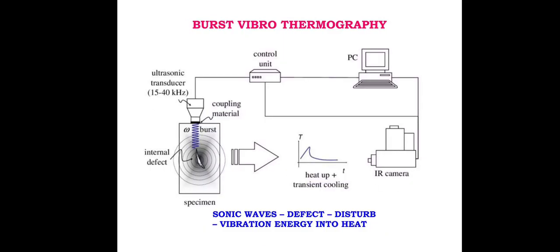Burst vibro thermography. In burst vibro thermography, a burst of ultrasonic waves are injected into the test specimen for a short time varying from milliseconds to a few seconds. This picture shows the schematic arrangement of burst vibro thermography. In this method of testing, the ultrasonic sound wave is produced by a transducer made of a stack of piezo elements and concentrated in a titanium horn that acts like a hammer. Hence, the part being inspected should be firmly immobilized without damaging the specimen to avoid cantilever effect, clapping, and sliding of the transducer.